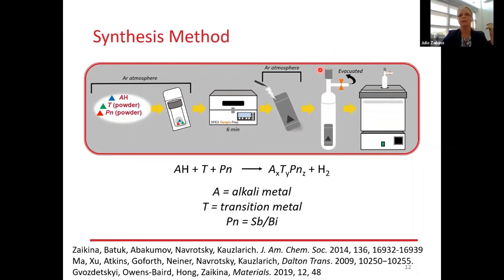So the need for this silica reactor is that we have the hydrogen gas evolved, which can diffuse through the niobium tube. However, to prevent the pressure buildup in the sealed silica tube, we use a silica container with a check valve, so hydrogen can diffuse out, but air or oxygen cannot diffuse in.